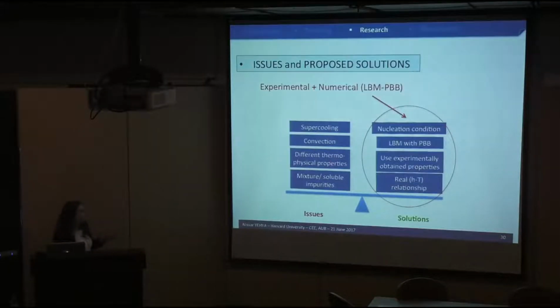So what are, in summary, the modeling issues that were faced here? The soluble impurities, and we solved it by adapting the real enthalpy-temperature relationship. Of course, adapting different thermophysical properties for solid and liquid phases. So we use the experimentally obtained thermophysical properties in order to better predict the performance of the phase change material. The convection was treated by the lattice Boltzmann method with a partial bounce-back approach for the mushy zone. The supercooling was treated by adding this nucleation condition that is translated into this curve that we've seen in the previous model. So we adopted a numerical and experimental way at the same time.